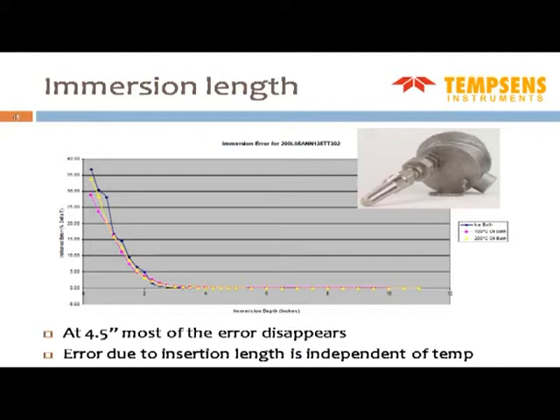So for a 12 millimeter tip, you can see that if we are not inserting more than 10 times, you are going to have a lot of error. It's the error in percentage, and if the insertion is not proper, then we will have a lot of error in the reading. So immersion, as Mr. Clem told, should be about 10 times the diameter of the tip. Plus you have to add, in case of RTD, another 20-25 millimeter for the sensor length. Then only you can get the proper temperature accuracy.